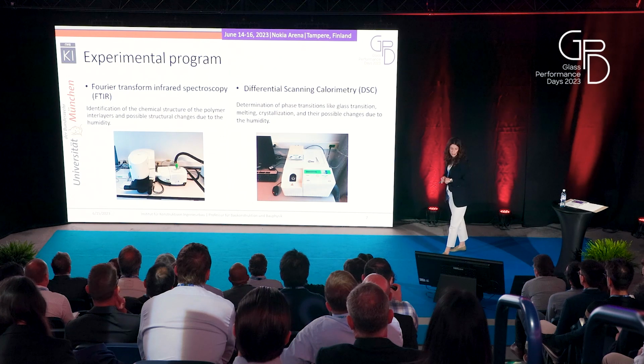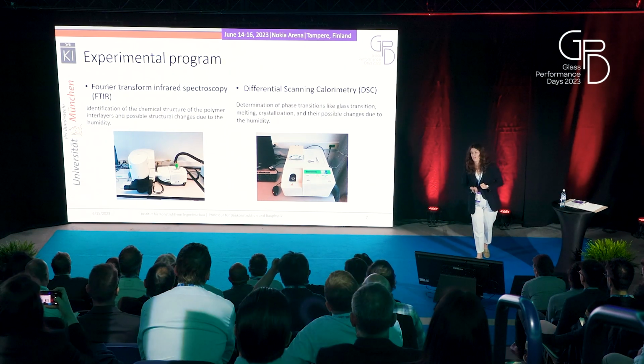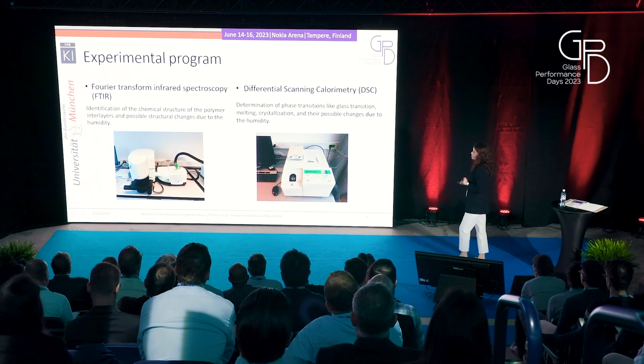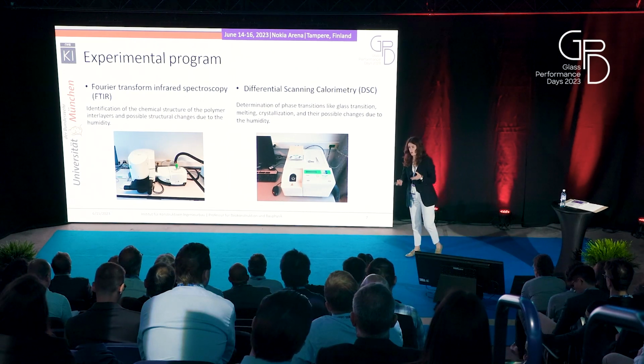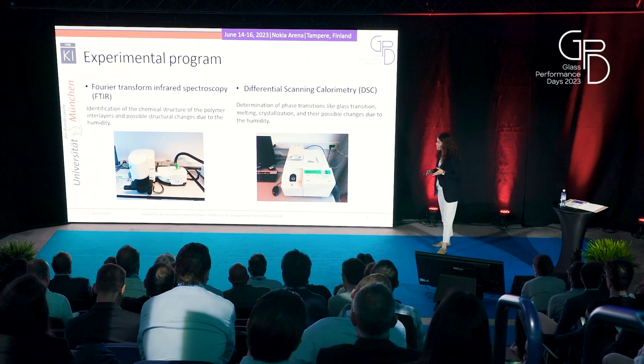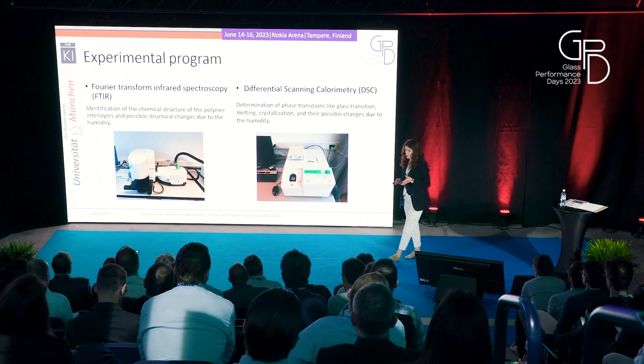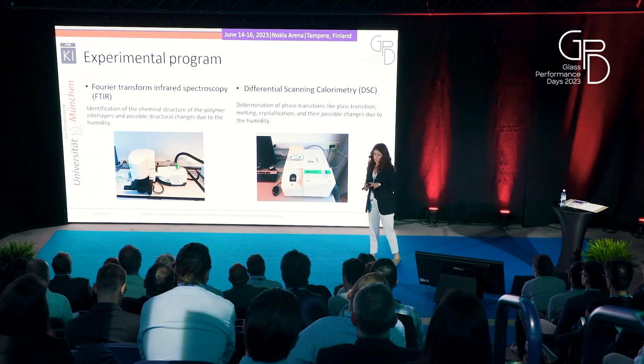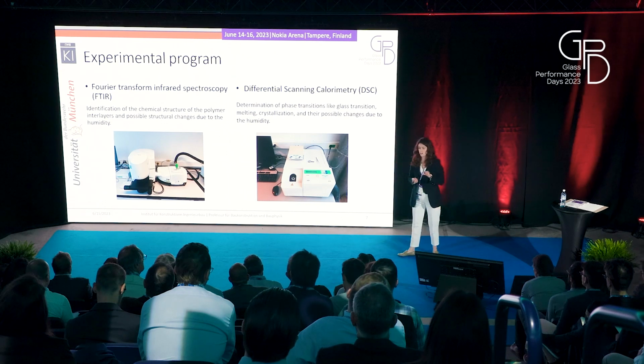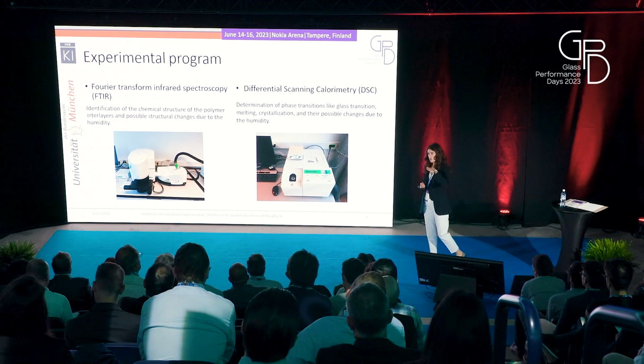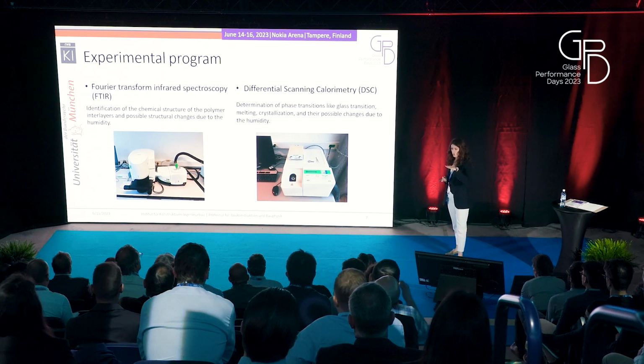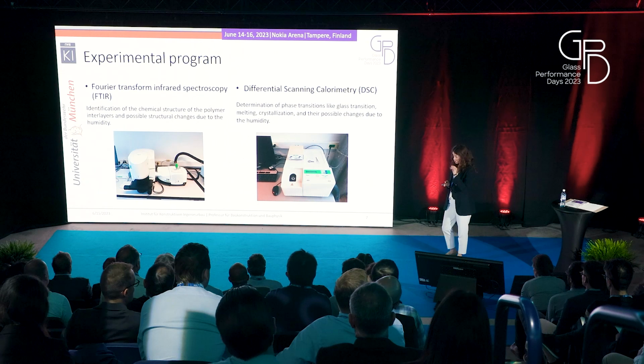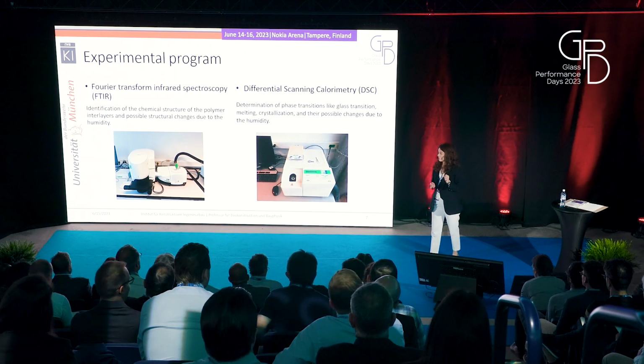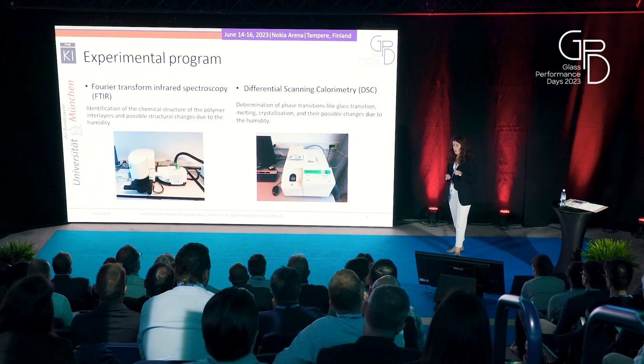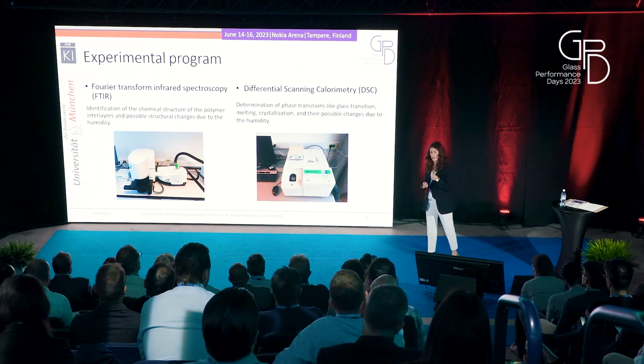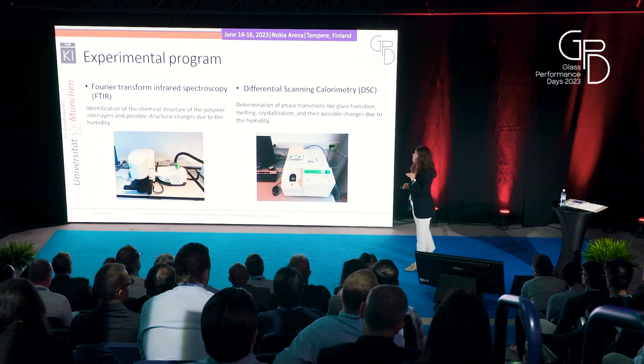In general, infrared spectroscopy is done for the identification of the chemical structure of the polymer. This time we did it for that, but it was also important for us to see whether there are possible structural changes due to humidity exposure. It's important to note that infrared spectroscopy measures a very thin surface layer of the material. The thickness of that is just a few molecules. So maybe with that we cannot measure the moisture uptake, but if there are some changes on a structural level, we can see them, even though it's a pretty thin layer.